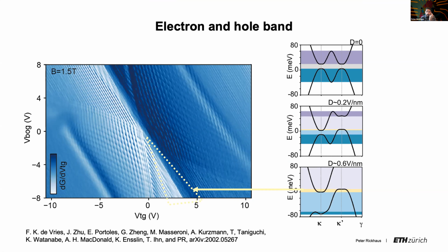Especially what is different as opposed to these magic angle devices is that here you have really a range of twists where it works, right? I showed data of a 2.3 degree device. It also works at 2 degrees. The results look very comparable, and for the magic angle devices, you really need to be at exactly the right twist. And already 0.05 degrees off makes a large difference.